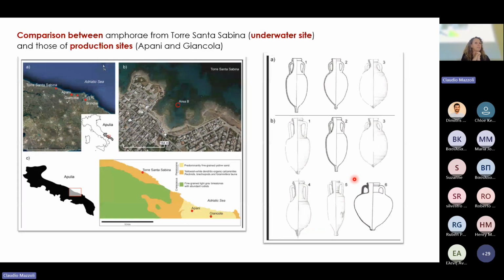Let's see what we have done. We took samples from an underwater site in Puglia at Torre Santa Sabina and made of this type of amphoras, which were produced locally in Apani and Giancola, two sites nearby in Puglia. We took also some samples from Apani and Giancola, and we made the comparison between the two types of amphoras.